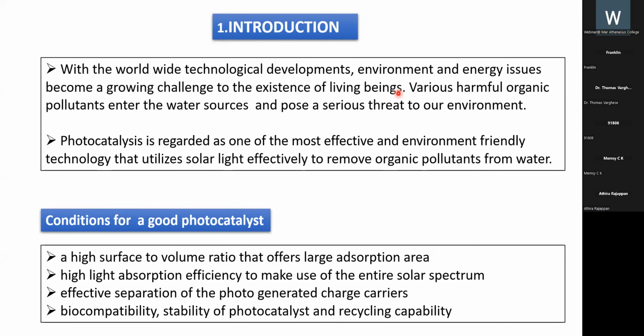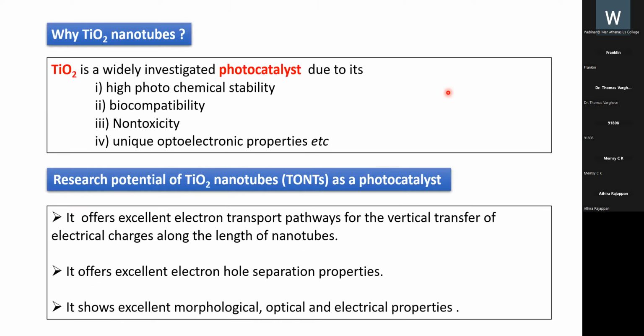work. Introduction. With the worldwide technological developments, environment and energy issues have become a growing challenge to the existence of living beings. Various harmful organic pollutants enter the water sources and pose a serious threat to our environment. Photocatalysis is regarded as one of the most effective and environment-friendly technologies that utilizes solar light effectively to remove organic pollutants from water. The conditions for a good photocatalyst are: it must have a high surface to volume ratio that offers large absorption area, high light absorption efficiency to make use of the entire solar spectrum, effective separation of photo-generated charge carriers, biocompatibility, stability of the photocatalyst, and recycling capability.